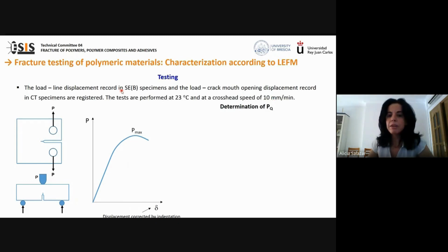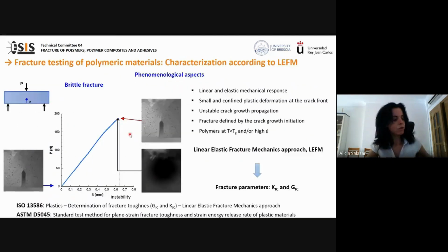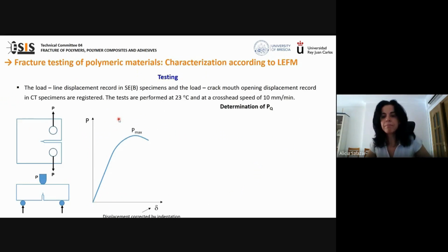The load line displacement record is obtained, as is shown in this graph, and in the ideal case, I want to show, the load displacement record is linear with a sudden drop of the load at the very instant of crack growth initiation. In this case, the maximum load is used for the determination of the fracture parameters. But in most cases, there is no linearity in the curve, and some restriction must be imposed for the application of this approach. Firstly, I'm going to describe how to determine the critical stress intensity factor K1C.